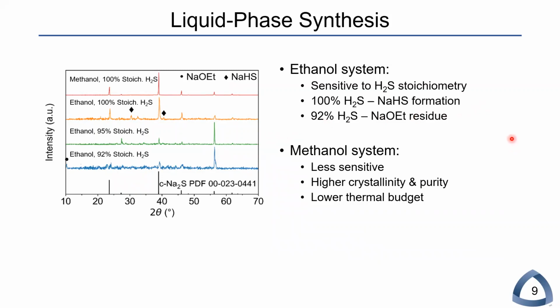However, using the methanol system was found to be much less sensitive to these parameters, resulting in higher crystallinity and higher purity material with 100% addition of H2S, and with an added benefit of a lower thermal budget due to the higher volatility of methanol compared to ethanol.